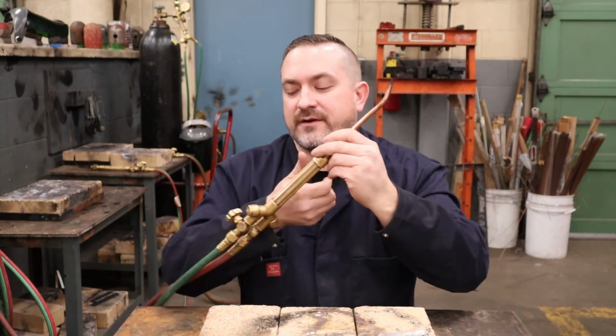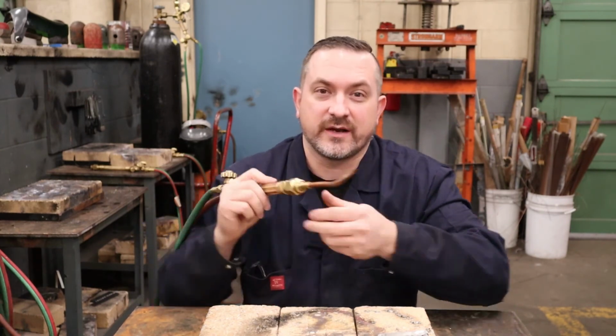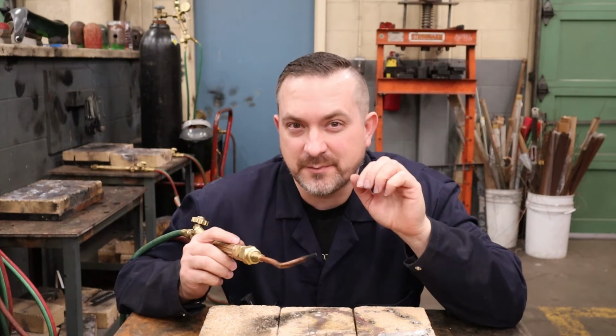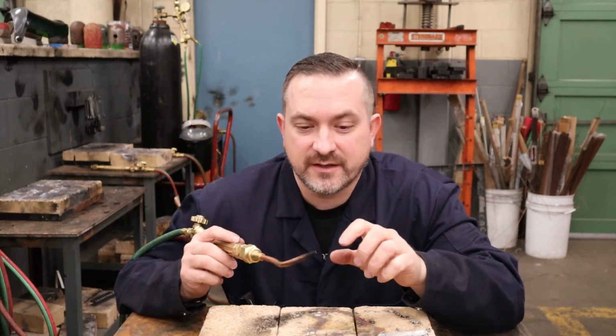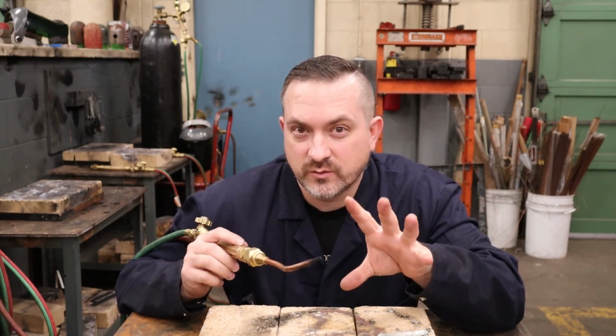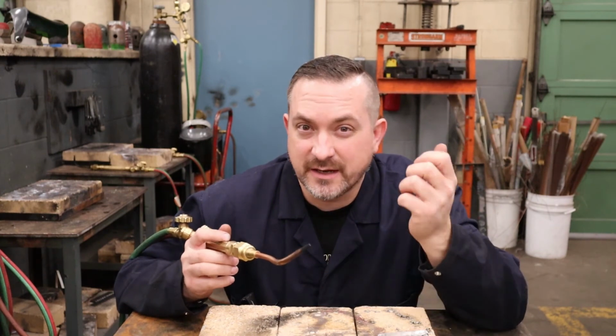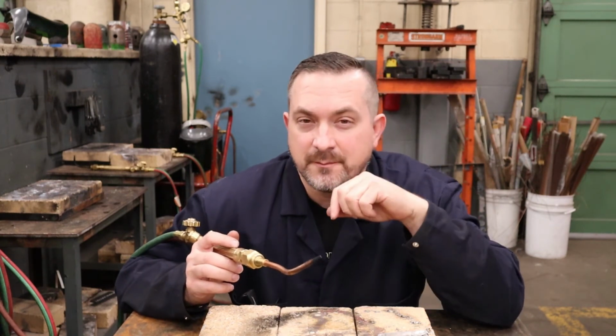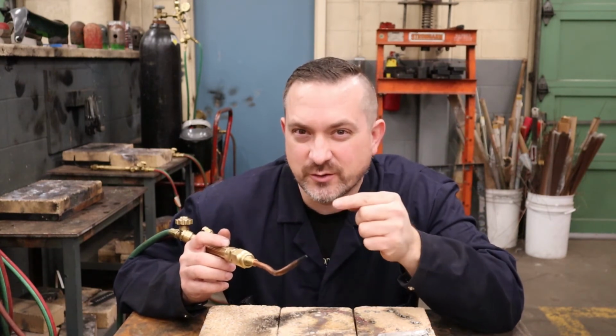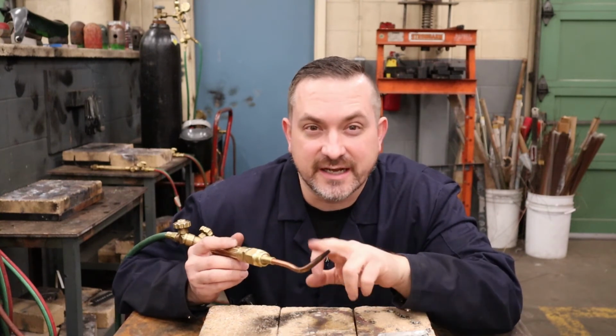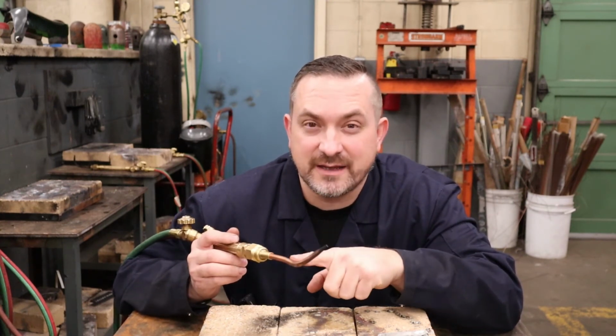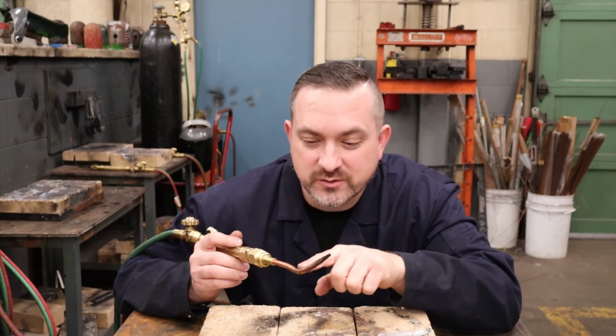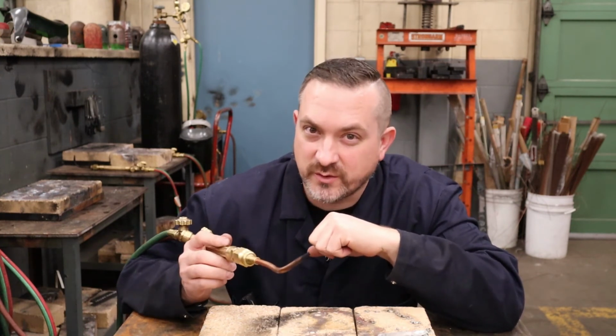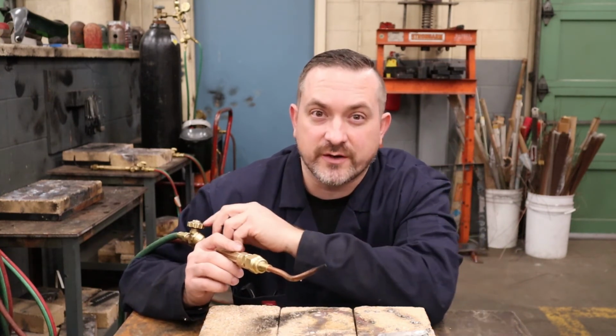If that happens, very quickly shut off your gases so we don't have any future issues. A couple of things could have happened. First off, you might have just had the flame blown out, in which case it's just the gases coming out and you're okay, just shut it off. But sometimes that popping continues and you'll hear a brrrr inside of here. What's happening is there's a flame and little mini explosions right in your welding tip. That's not really good for the long term. You've got to shut that off right away.